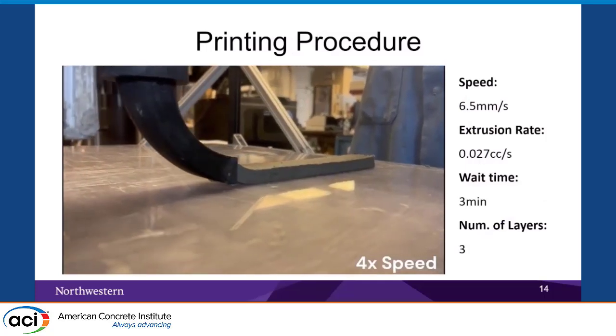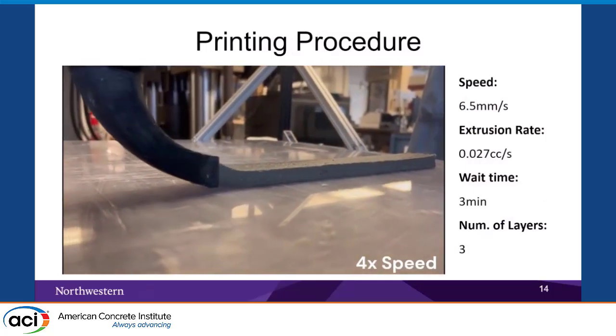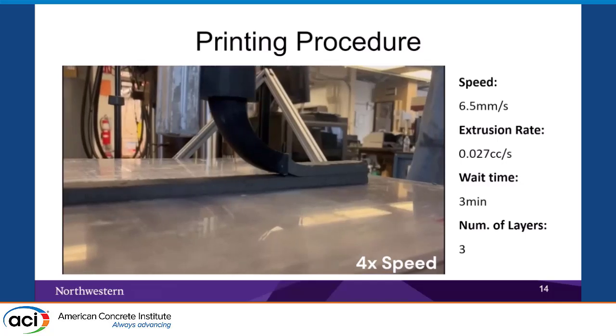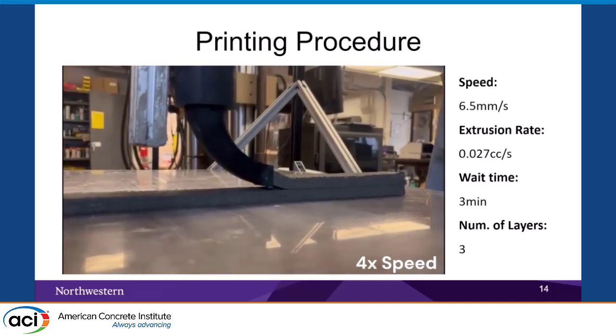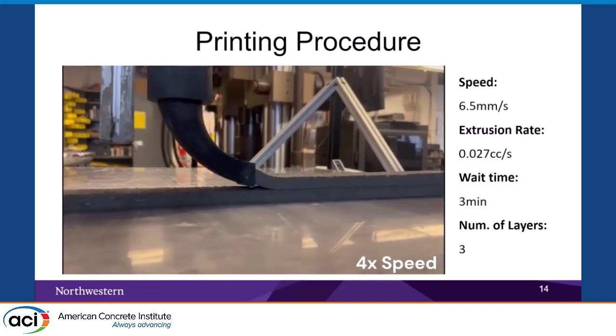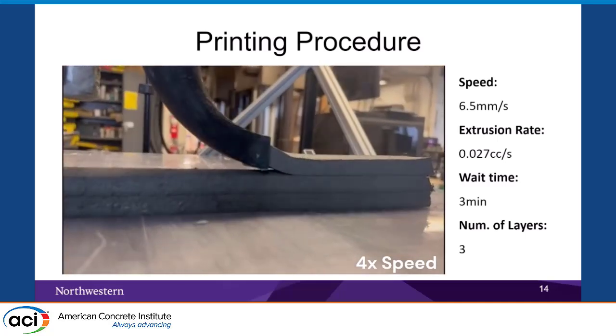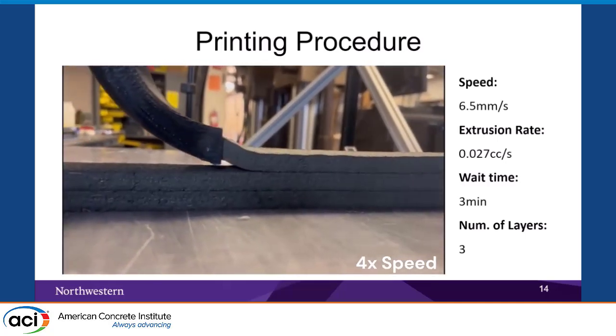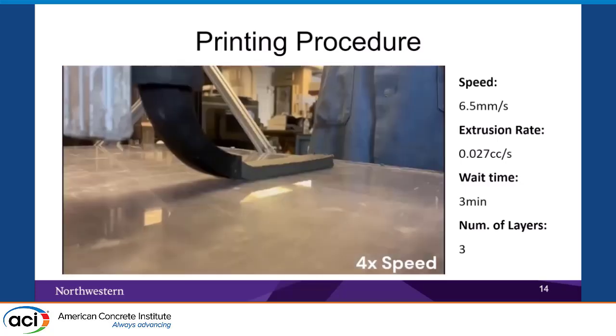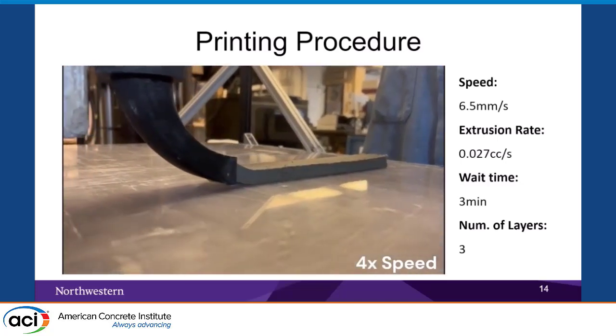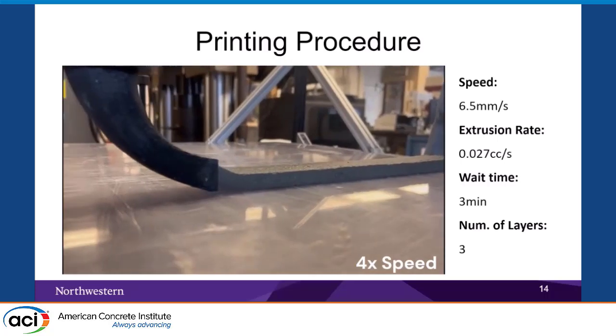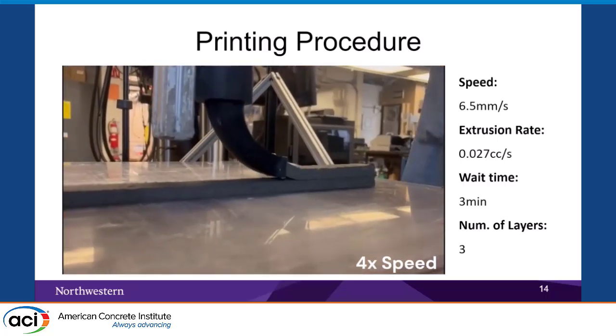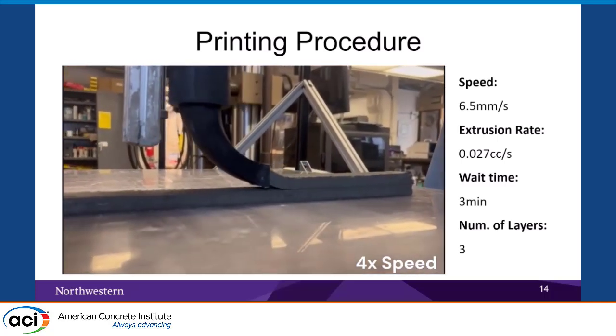And this is a short video showing the quality of our printing. Here we printed 3 layers with a waiting time of 3 minutes between each layer, and the speed is 6.5 millimeters in length per second. Then after we printed the 3 layers, we cut samples out of those layers and performed our mechanical characterization.